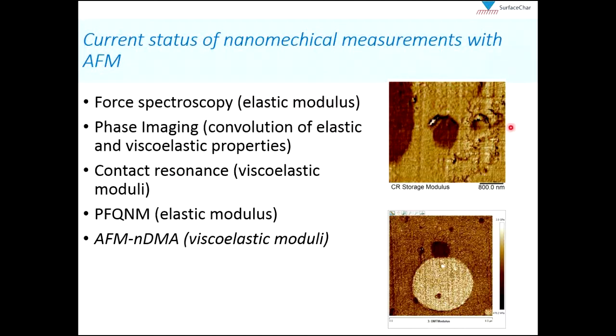And here is a contact resonance image, where the storage modulus, E prime, has been mapped on the surface of a multi-component polymer blend. There is also PeakForce QNM to measure the elastic modulus. And here is an image of a 3-component polymer blend measured with PeakForce QNM. Now, the focus of today's webinar is a new method, a new addition to our capabilities, which is AFM-nDMA to measure viscoelastic moduli.